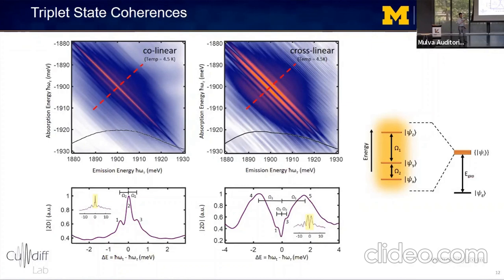So peak 2 in the middle lies on the diagonal. So this corresponds to absorption and emission in and out of the same triplet state. It's then suppressed in the cross-linear spectrum due to the orthogonal dipole moments of the triplet states. So peaks 1 and 3 lie at plus and minus omega 2. So they correspond to coherent coupling between states X and Y in the level diagram on the right. And peaks 4 and 5 lie at plus and minus omega 1. So they correspond to coherent coupling between states Y and Z.